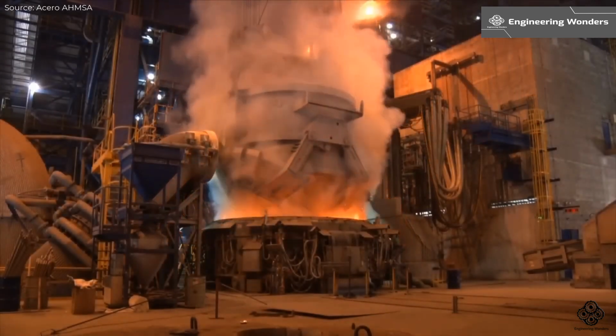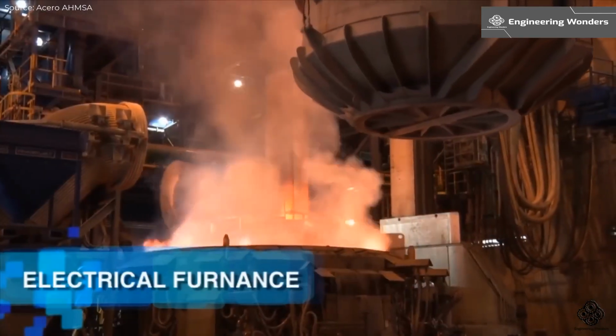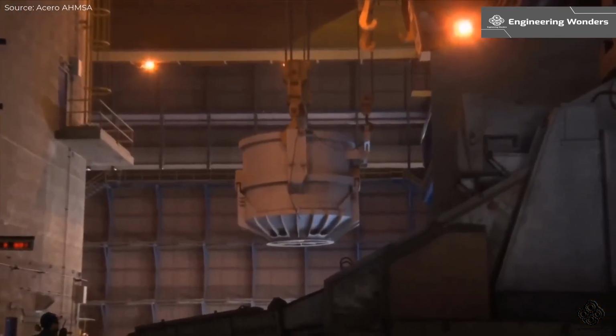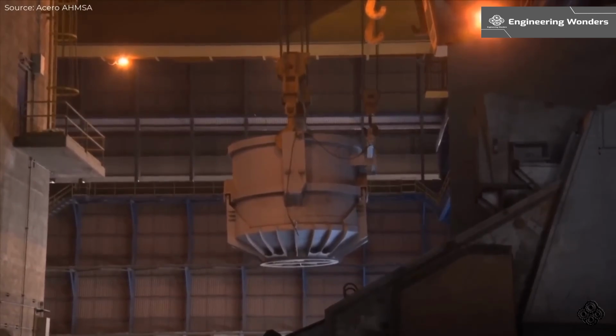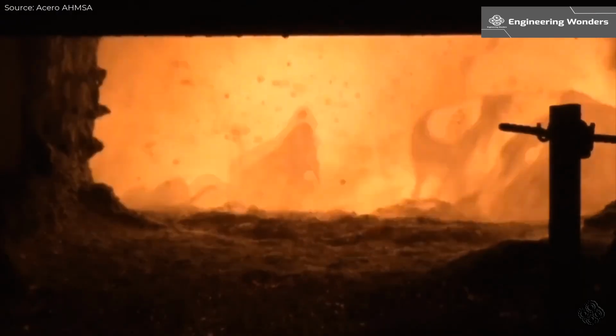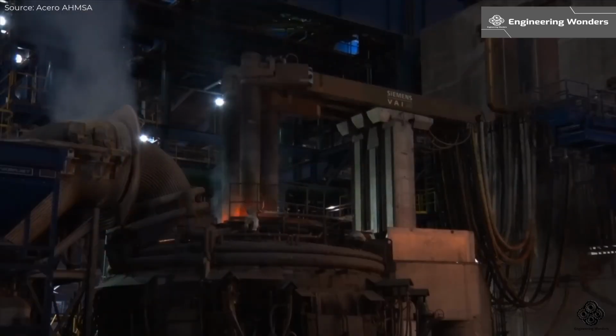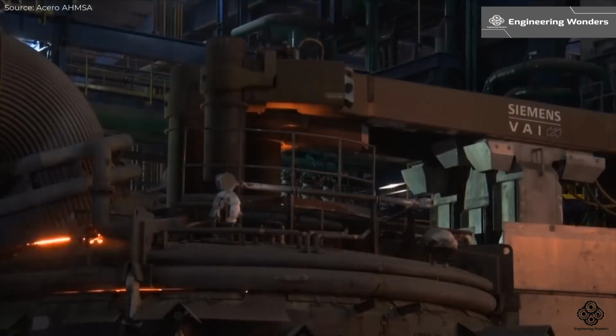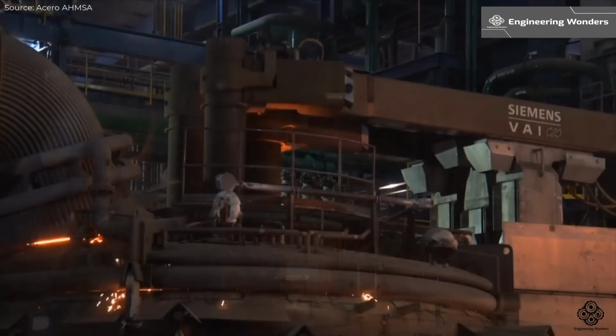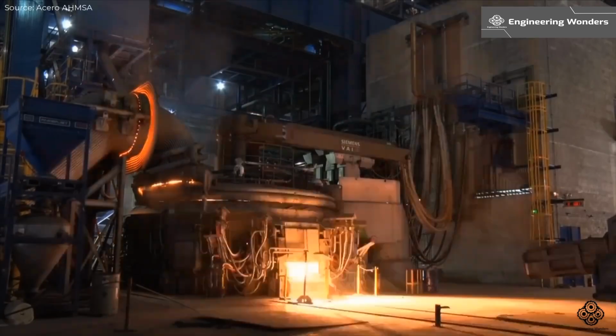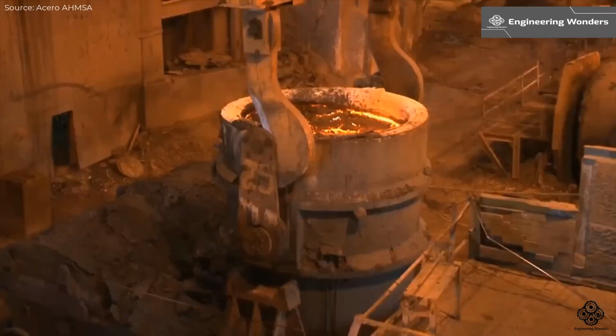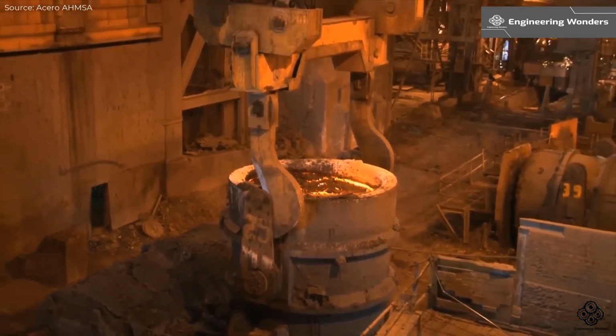Electric arc furnace, EAF. The EAF process begins with a mixture of scrap metal, iron briquettes, or liquid pig iron, typically at 150 metric tons per cast. The furnace uses 3 graphite electrodes to apply 140 megawatts of electric energy, melting the load to produce steel. The liquid steel is then transferred into special ladles.